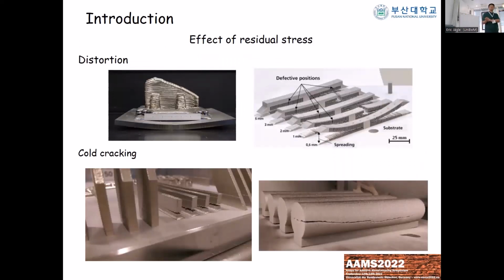And there's always some residual stress issue in the laser powder bed fusion system. Depending on the three-dimensional shape of our component, we more or less always have complex residual stress inside our component in the as-built state. This can produce some distortion when we cut the component from the base plate, or in the worst case, in brittle material, sometimes cracking as well.